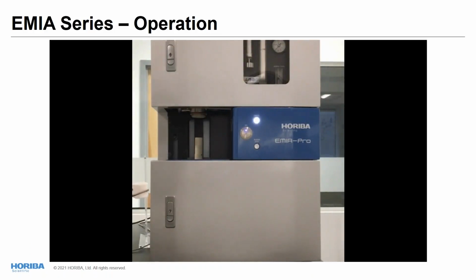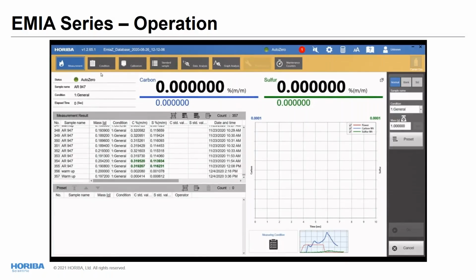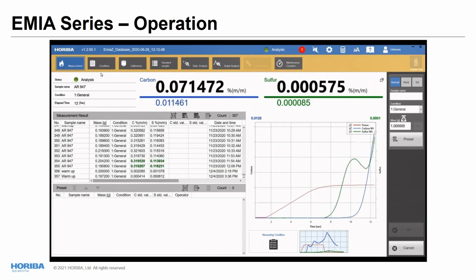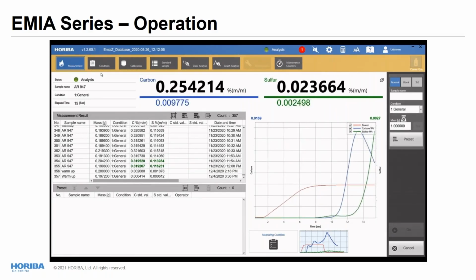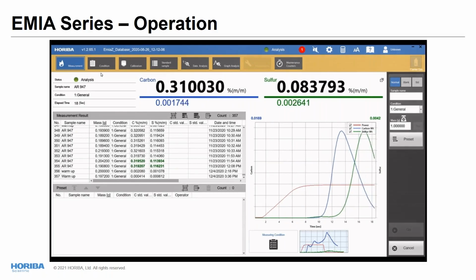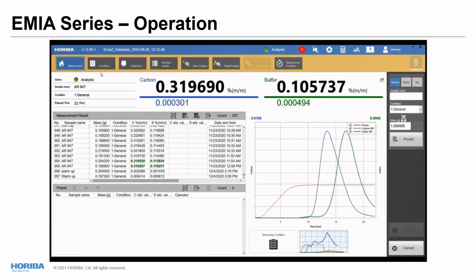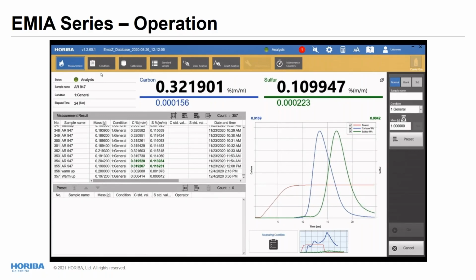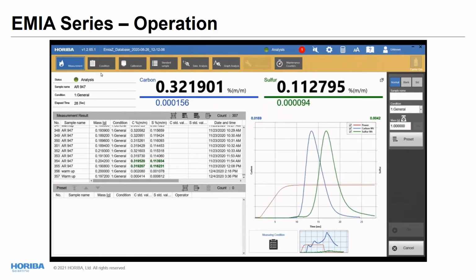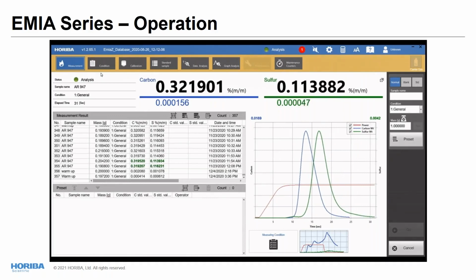What you can see here is a video that was shot in our demo lab in New Jersey, and you can see how easy it is to perform analysis. Typically, you have a crucible with a sample that you introduce in the furnace, and you can start the analysis by pressing the button on the instrument or clicking in the software. As soon as you start the analysis, the temperature will rise. You can see the temperature increase here, and the various elements, carbon and sulfur, will be detected by the system. You can see the green curve for the sulfur and the blue one for the carbon here, with values in the 0.3, 0.1% level here. When analysis is done, you can just open the furnace, remove the crucible, and move on to the next sample by placing it on the stand and pressing the button again.